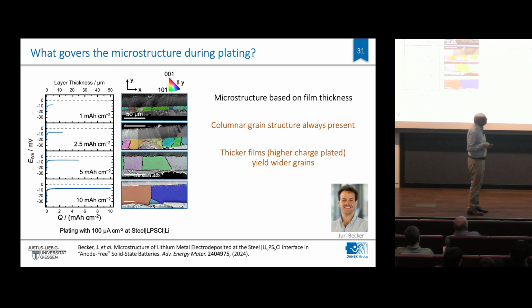And what we found, to make that story short, is first of all, we only saw more or less always one grain across all the film thickness, vertical grain boundaries. And when we let the layers grow thicker, the grains became bigger. So they changed their size with thickness of the film. And that was work by Jun. This is, by the way, on steel deposited lithium.